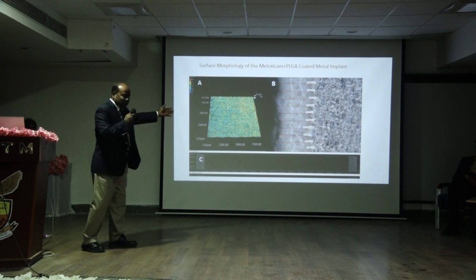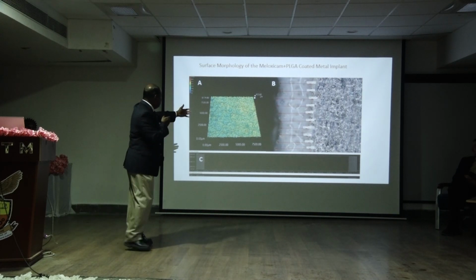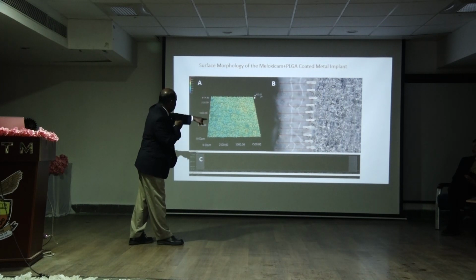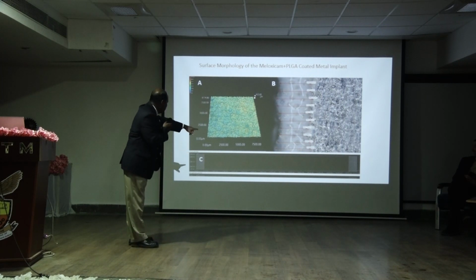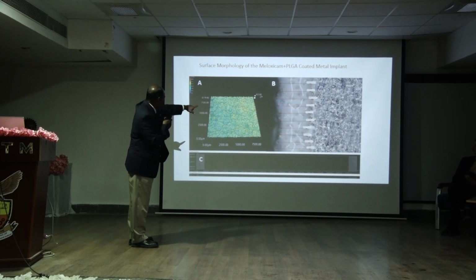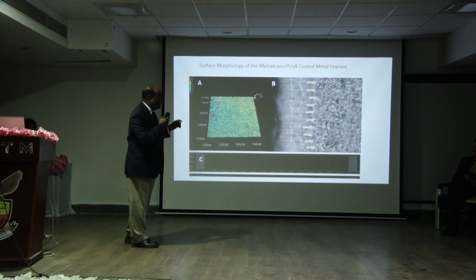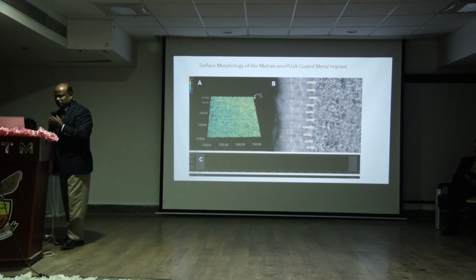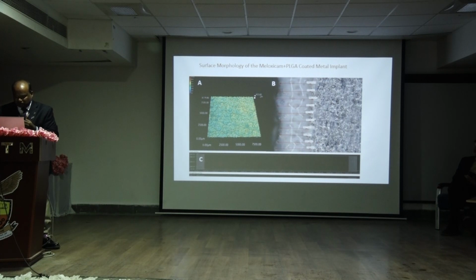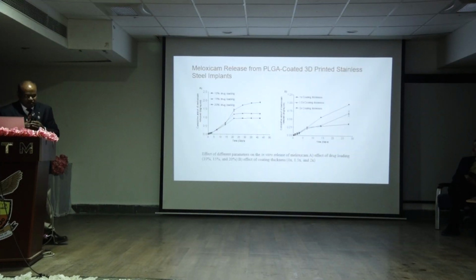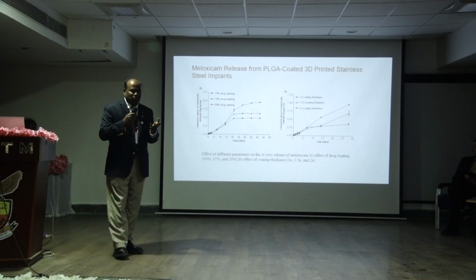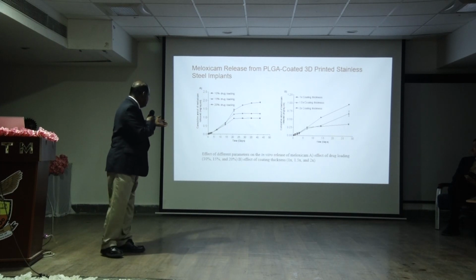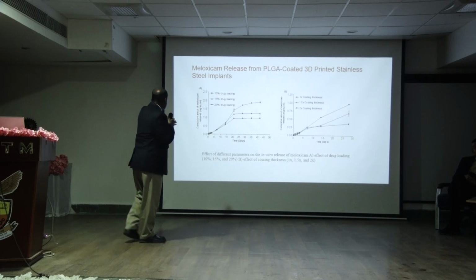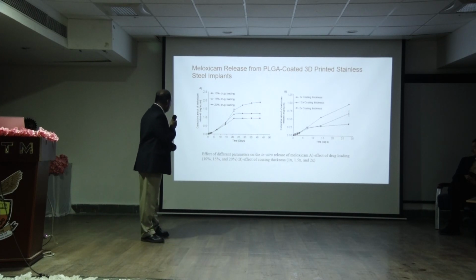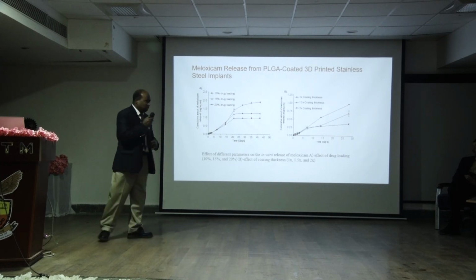So as you can see from the microscopic image here, we measured the surface roughness and we measured Ra value and versus Rq value, which are not seen here. As you can see the distinct layer of the polymer which is deposited onto the surface in this case, and so that way we know that the drug is deposited as a uniform layer onto the implant. So the drug, because we used a biopolymer, as a result, as you can see, the drug is delivered for several days, up to more than 45 days, the drug is continuously delivered from the surface.